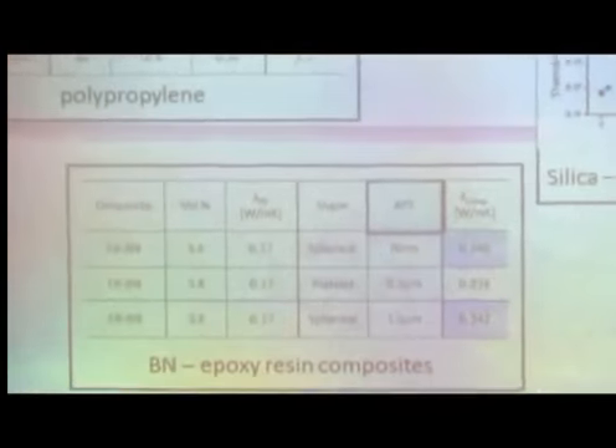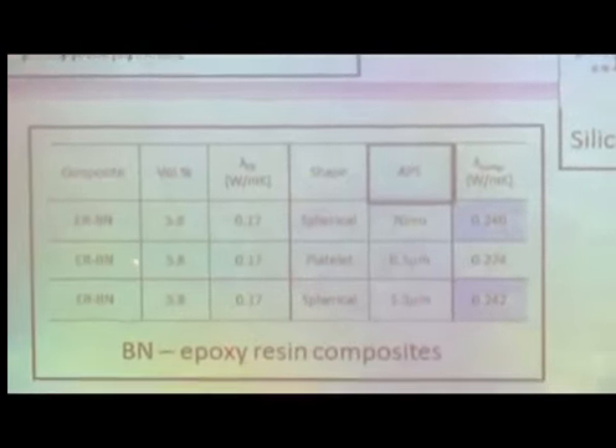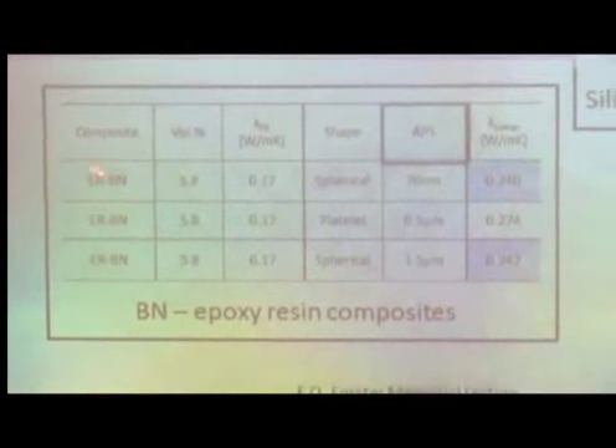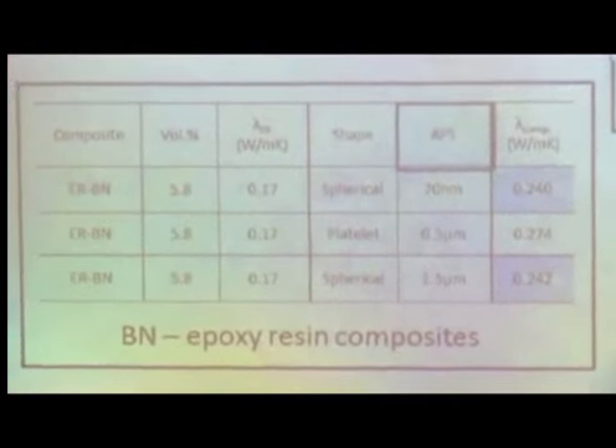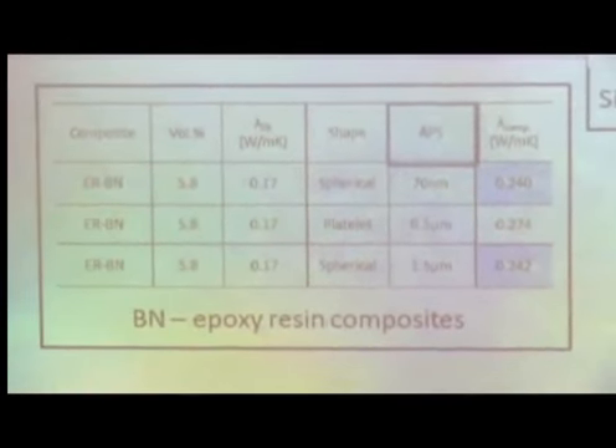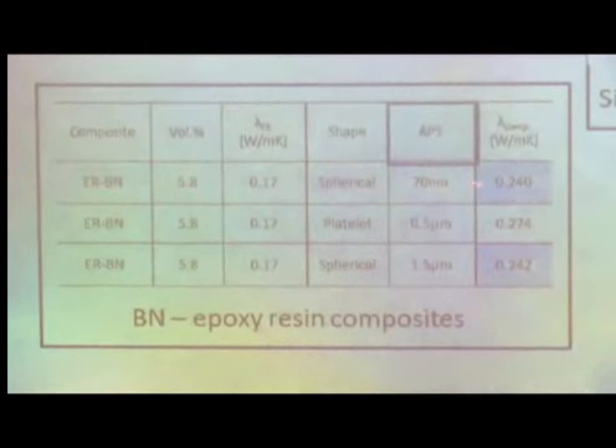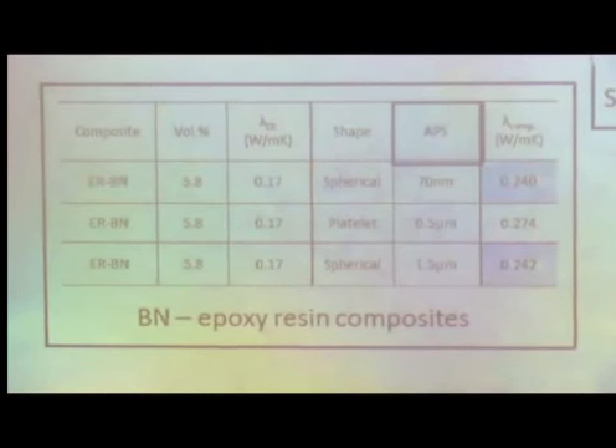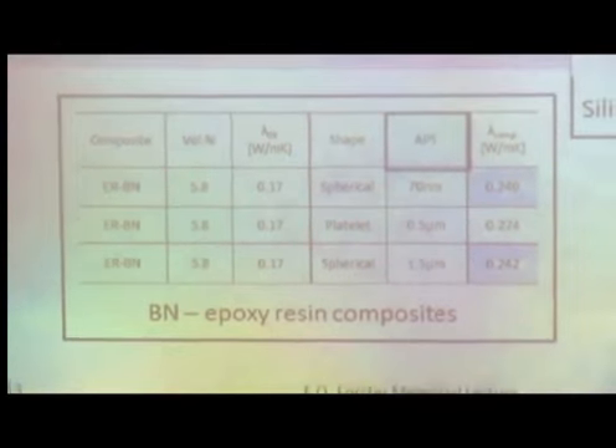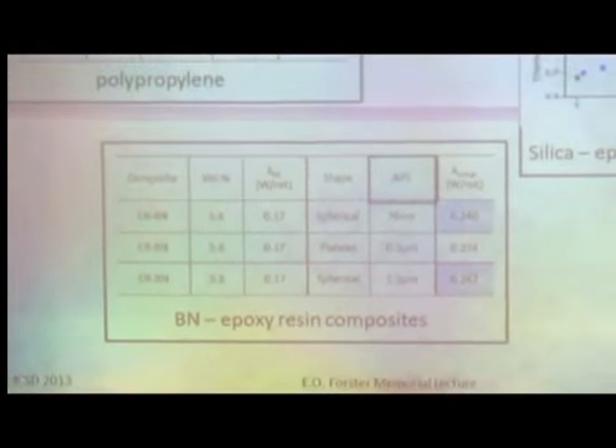here in this table, we are focusing on epoxy resin boron nitride nanocomposite. Look at the first row and the last row. These are both spherical particles, but in the first row we have nanoparticles, in the last row microparticles. Same fill grade. We see that they have comparable thermal conductivities. This goes totally against, at least my expectations.